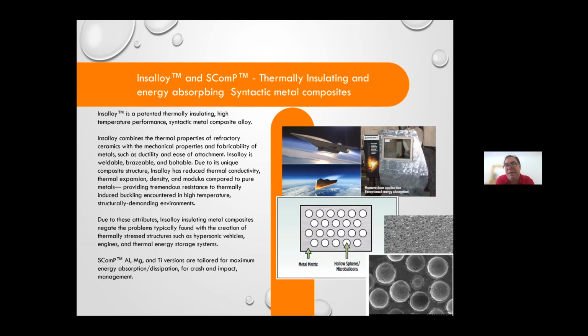On the other end of this is if we fill these up with aerogels, ceramic aerospheres, or microballoons, we can make thermally insulating metals that also have tremendous energy absorption capabilities. So one of the early demonstrations is the backing. These are strong enough to actually support a ceramic, but can absorb 1/3 to 1/2 the energy of a fragmenting projectile or a kinetic weapon strike, basically greatly reducing or eliminating backface deformation and intrusion.